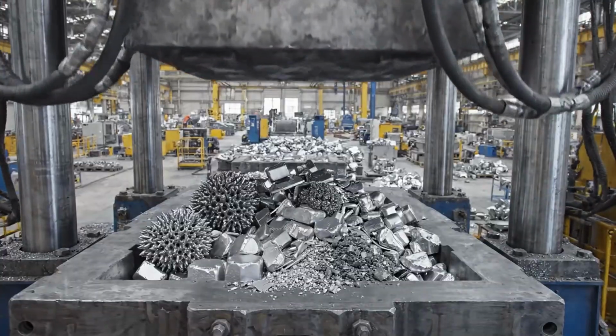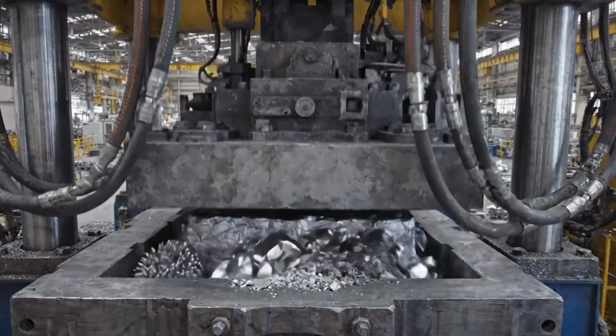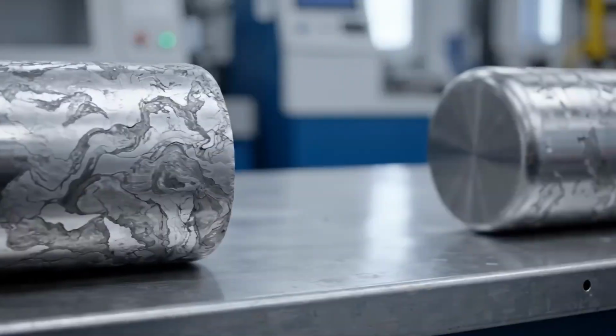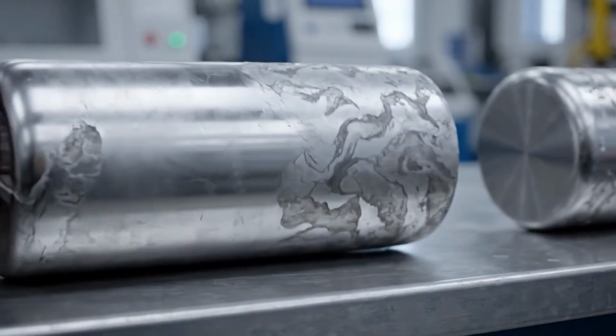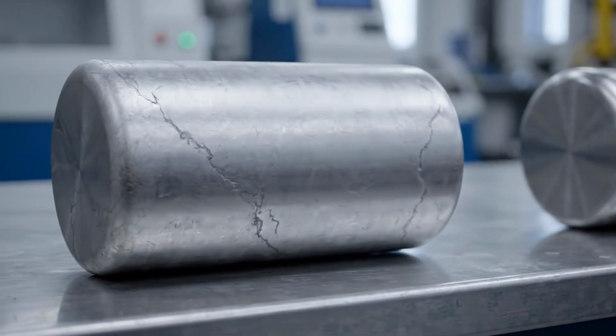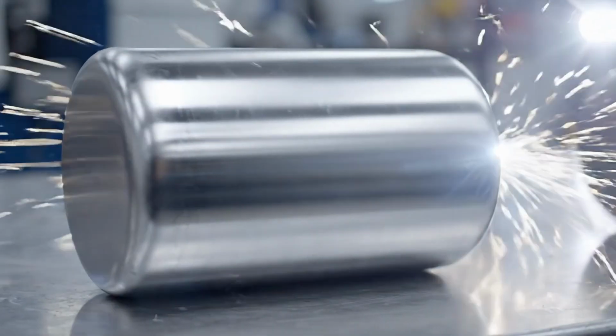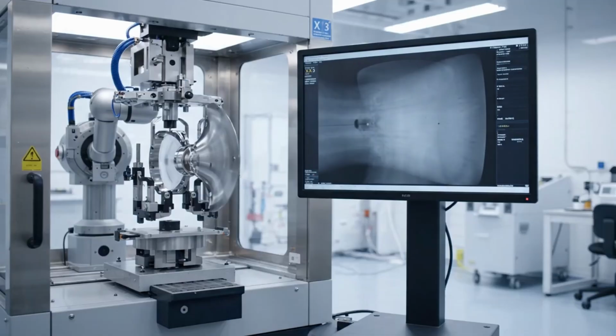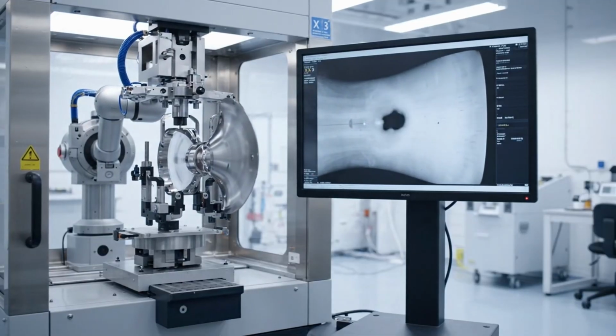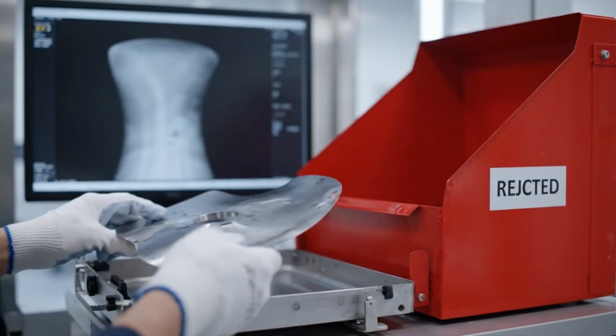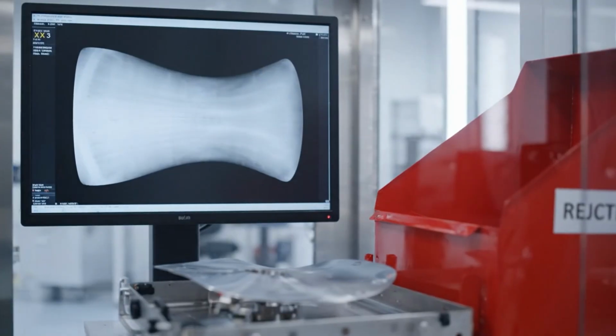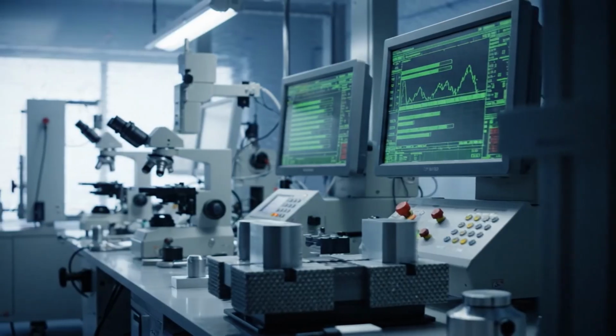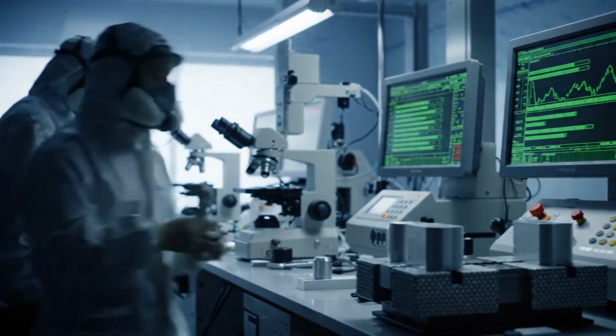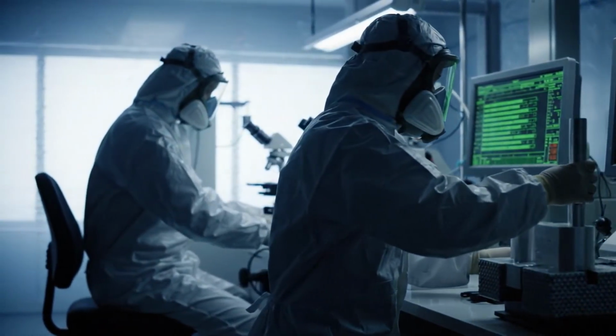Often, the ingot is melted more than once. Double or triple melting helps to homogenize the composition, eliminate defects, and better distribute the alloying elements. In critical applications, even a small internal defect can be unacceptable. An aerospace part made of titanium cannot have inclusions, hidden cracks, or areas with irregular composition. That's why metallurgical control is so strict.